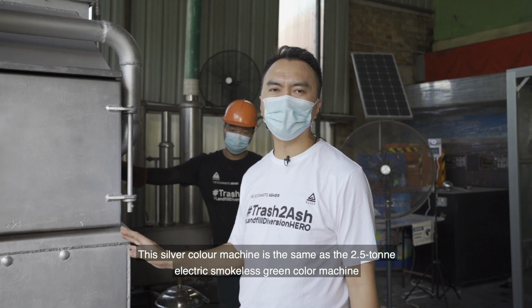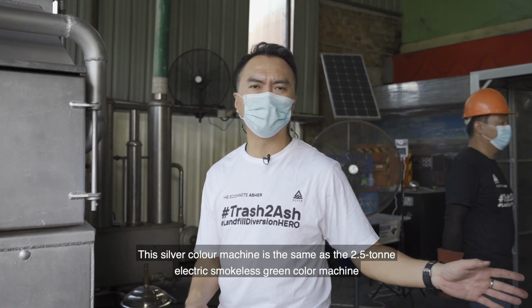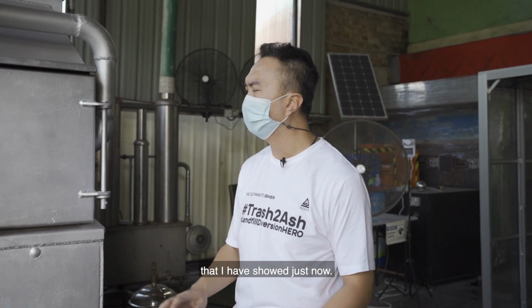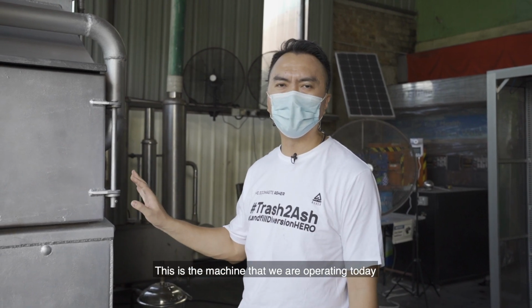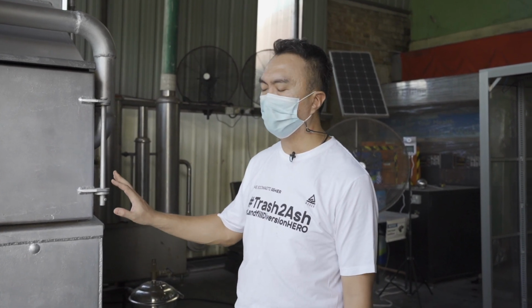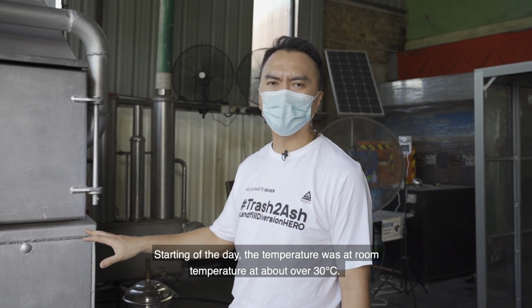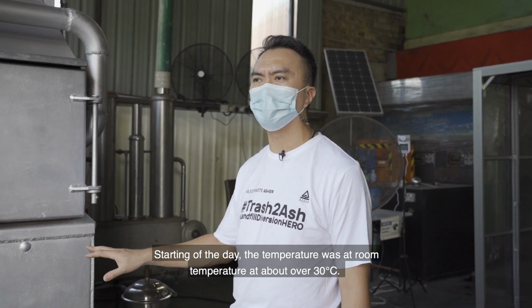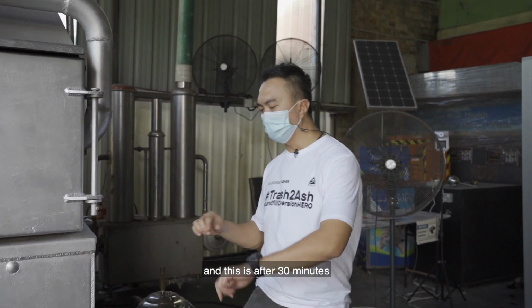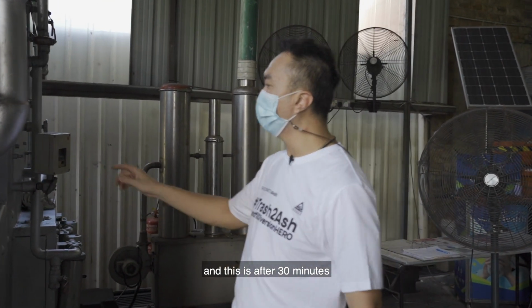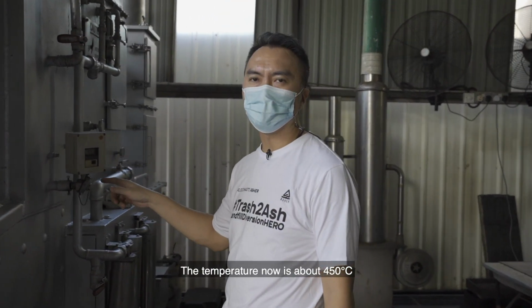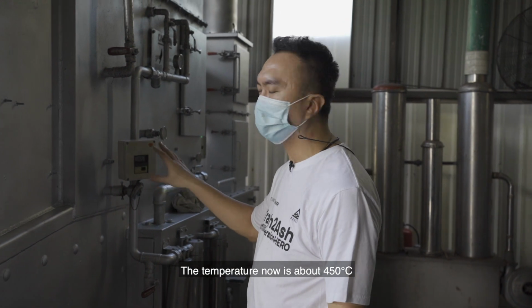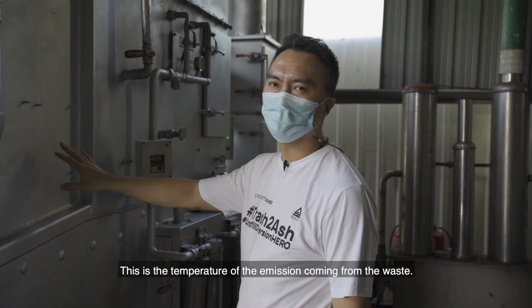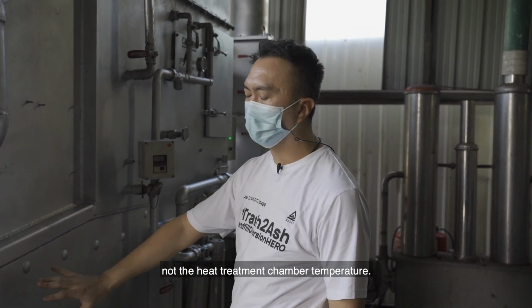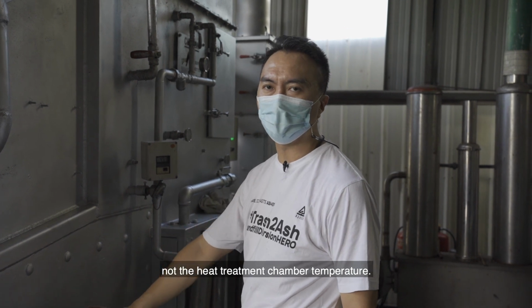This silver color machine is the same as the 2.5-ton electric smokeless green color machine that I showed just now. This is the machine that we are operating today. At the start of the day, the temperature was at room temperature, about 30 over degrees Celsius. And this is after 30 minutes. The temperature now is about 450 degrees C. This is the temperature of the emissions coming from the waste, not the heat treatment chamber temperature.